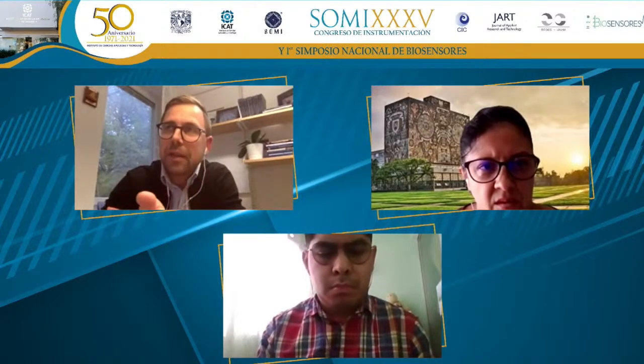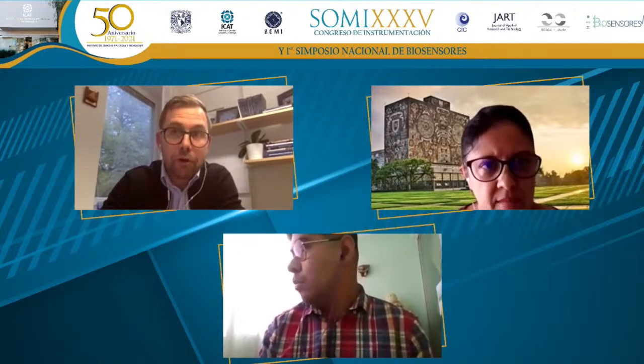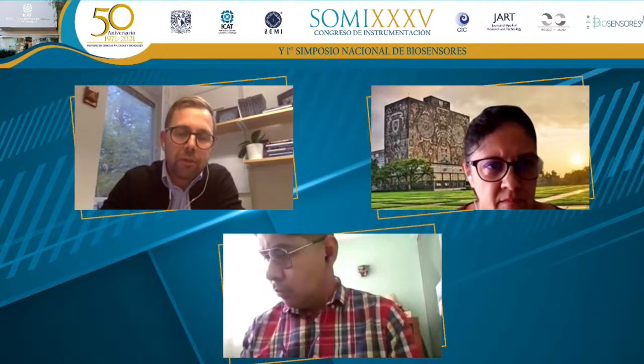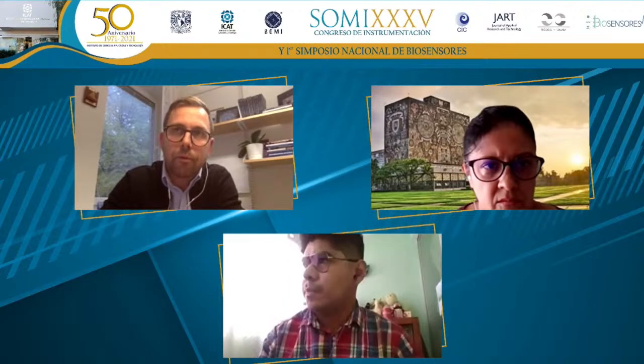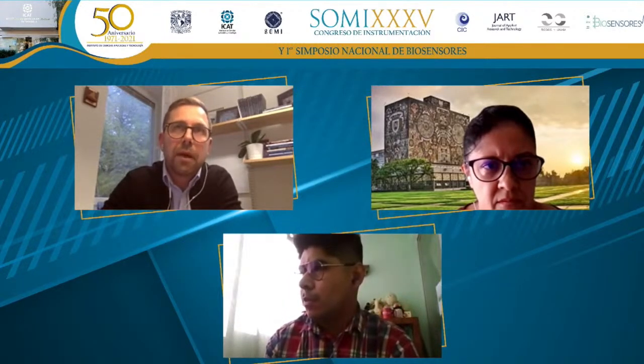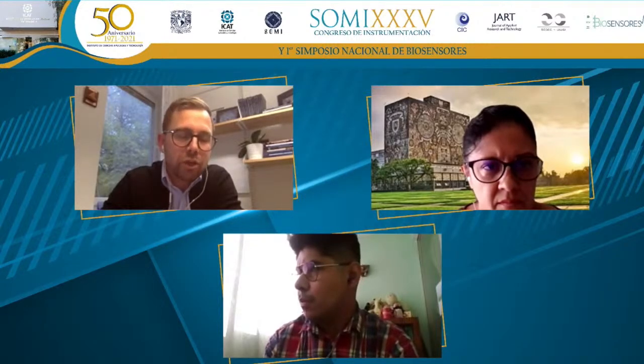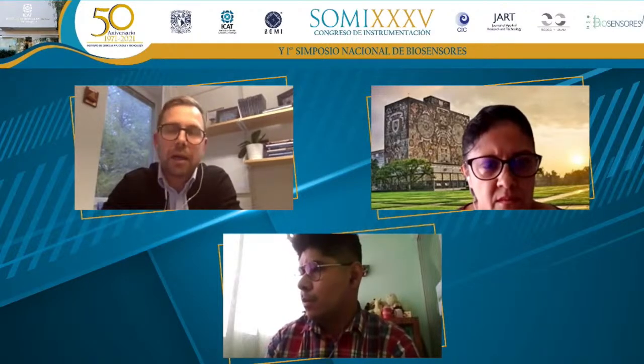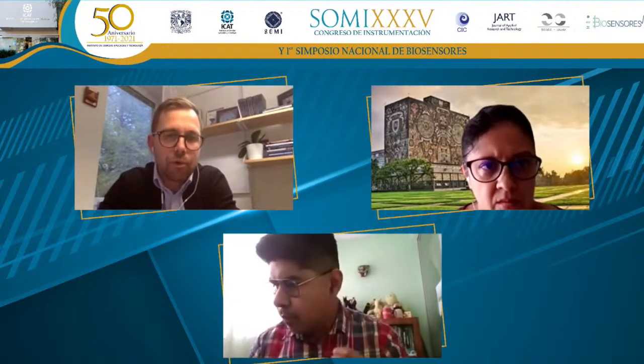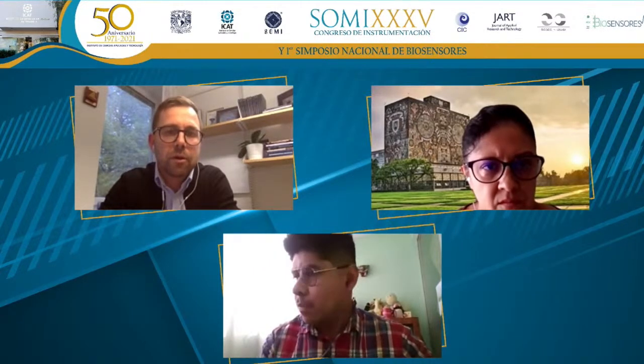Yeah. In the case here with the sensors we develop for bioprocess monitoring, we use protein A for detection of antibodies, at least to a large extent. And that's a fairly stable protein. We typically use these chips within 3 days. If we store them in the fridge, it's reproducible over 3 days. But of course, this is something we need to look into, if we can optimize storage conditions, and I assume that's possible. You can buy sensor chips from Biacore, for example, with protein A that lasts for years. So there are techniques to essentially preserve the proteins on the surface.